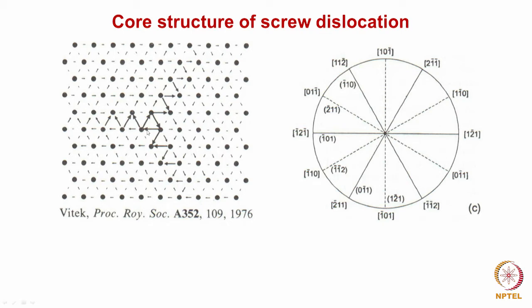Does it have a radial symmetry or not? When we look at the figure, it's obvious that it doesn't have a radial symmetry, and in these directions the displacements are very high, and in this as well as in this direction, and this corresponds to the plane on which these directions are lying, are 110 type of a plane.